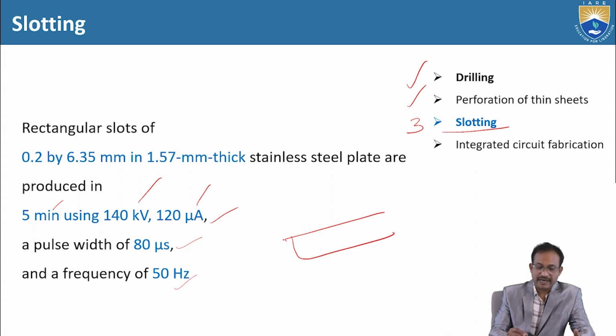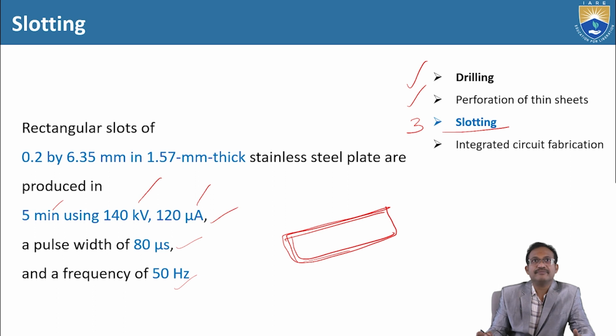So here, rectangular slotting. Rectangular slots of 0.2 by 6.35 mm in 1.57 mm thick. So here the thickness is 1.57 mm. This one is 0.2 mm, and this one is 6.35 mm. Stainless steel plates are produced in 5 minutes using 140 kilovolts with 120 microamperes, with a pulse width of 80 microseconds and a frequency of 50 Hz.